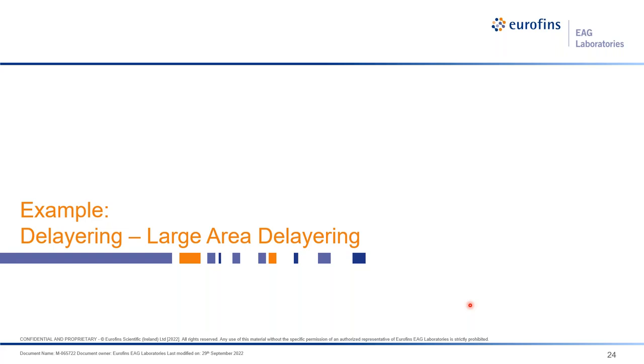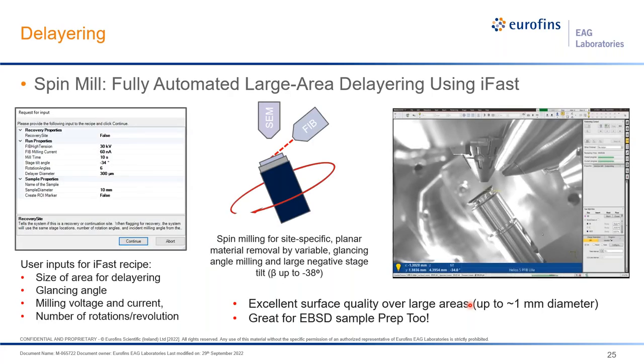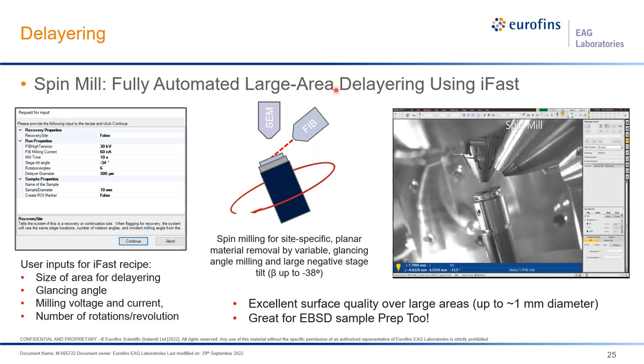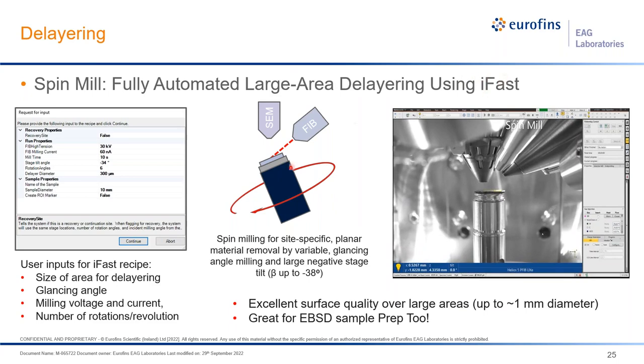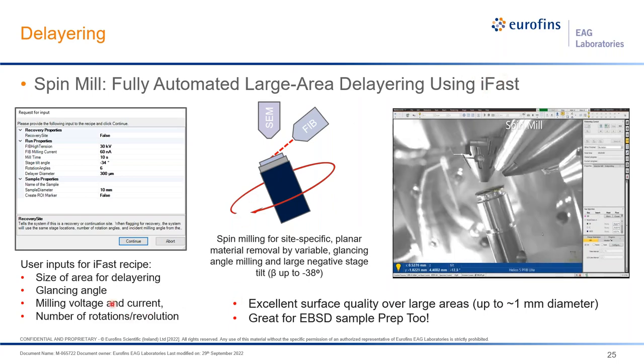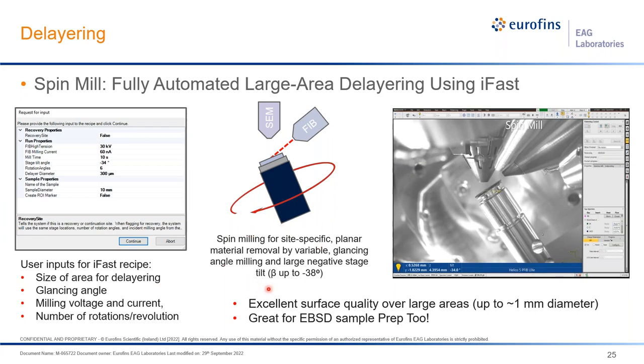So this is also in the case of large area delayering. And so we're going to look at first, how do we prepare our samples for the delayering process and subsequent SEM image acquisition? And what we're going to utilize here is FEI's fully automated large area delayering using iFast called spin milling. And so this is a really great way to quickly remove overlayers in a very planar way. And so this is really good for providing excellent surface quality of areas up to about 1 millimeter in diameter. This is not only great for semiconductor work, but also for EBSD sample prep as well.